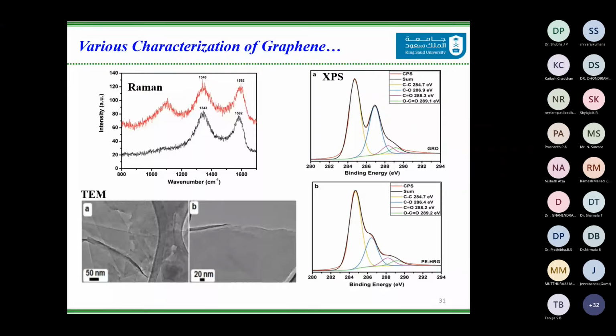Another interesting study that we did was the XPS analysis. So in the XPS analysis, we found that in the range between 284 to 290 electron volts, you get the carbon and carbon heteroatom signals, and mostly this heteroatom is oxygen.